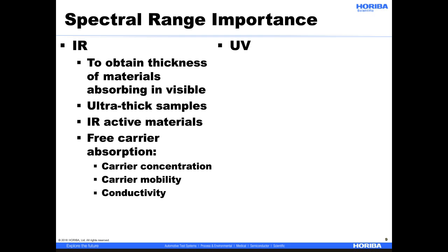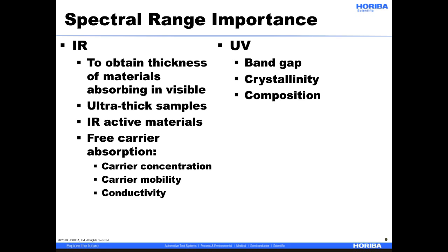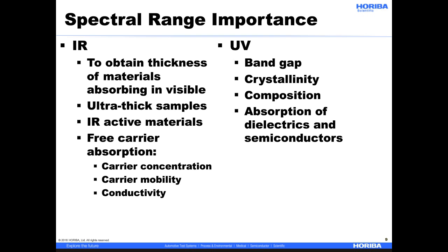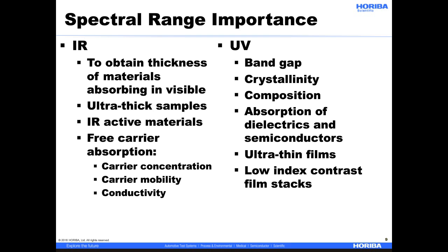On the other end of the spectrum in the UV, this is useful for bandgap determination, crystallinity, and composition determination. It's for absorption of dielectrics and semiconductors, ultra-thin films, low index contrast film stacks, alloy composition, and you can ultimately determine grain size as well.